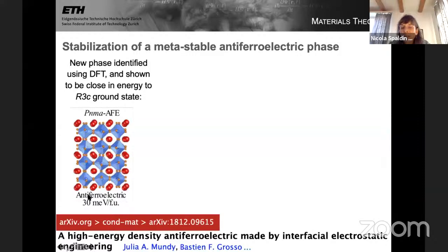We're allowed to call it antiferroelectric because at least in the computer, Bastien found a pathway by which he could take this phase with its opposite dipoles into a phase which was ferroelectric with the dipoles lined up. And that's a requirement for a system to be antiferroelectric, not just antipolar.